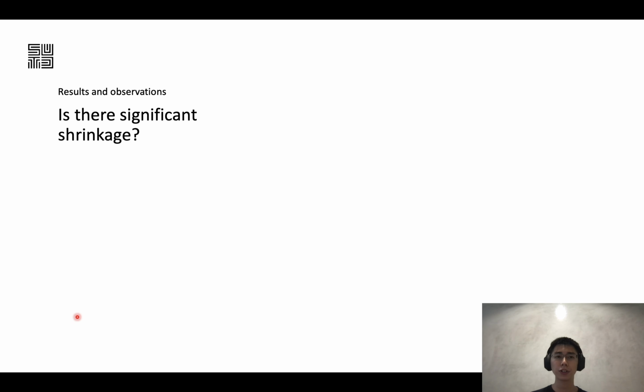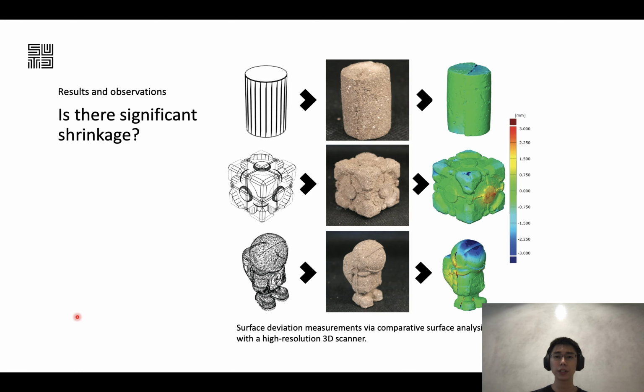Now, as in casting, another question that follows up from this experiment is whether there is significant shrinkage between the model and the cast object. So to do this, we cast a few objects of increasing complexity of curved surfaces and multiple grooves just to test out how much the material shrinks before and after drying. And we compare them to the original model. And what we found by comparing the volumetric scans is that there is a maximum of 3 mm surface deviation, and a 10% contraction in volume. Now, this would be useful information if we were to design our future molds.